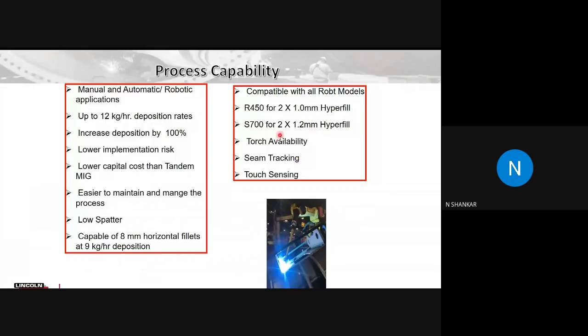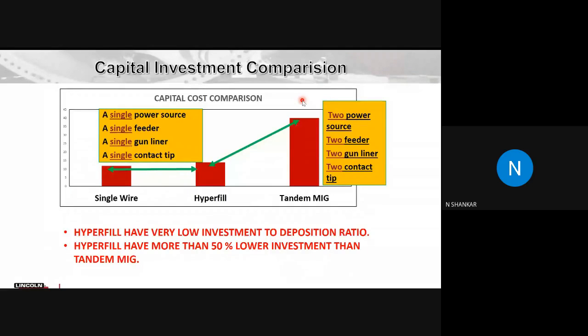When you look from the automation capability, it is compatible with all robots that you get in the market. You can do it with two 1 mm wires or two 1.2 mm wires. You have torches available for all models. You have seam tracking and touch sensing available with this process to support you. When you look at the capital investment part of it, it costs almost as much as a single wire system, but it will give you deposition at par with the tandem MIG, which means it's 50% lower than tandem MIG in terms of investment, but at par with the productivity part of it.